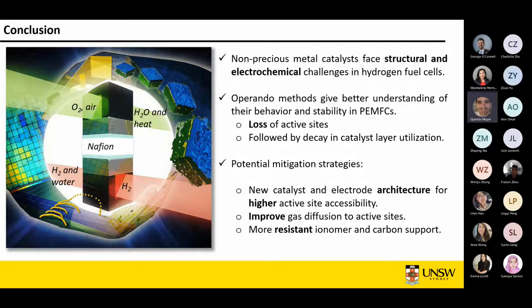And the kind of mitigation strategies. There are more things going on in the field, and we are looking at some of them, but the first type is making a brand new catalyst with much higher active site accessibility. That's things going on in some commercial companies, making much larger pores, and hopefully you don't have nanopore problems. Or you change the electrode structure completely, trying to make basically highways for proton conductivity, areas where you can conduct a lot more gas, and areas where you can conduct a lot more water out of the cell. So this is an area to look for, improved gas diffusion.